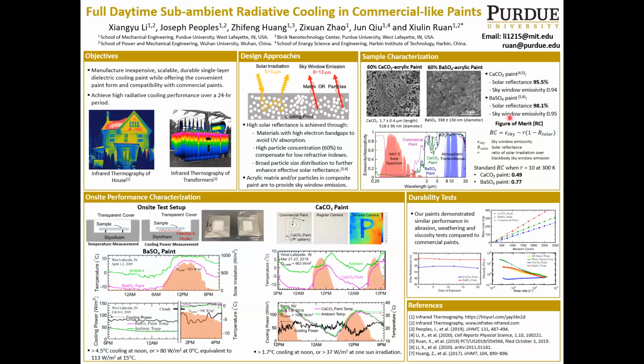We propose a standard figure of merit for radiative cooling as RC to include both sky window emission and solar reflectance. R is the ratio of solar irradiation over black body sky window emission, depending on different locations and weather conditions. With a positive RC, the coating is capable to reach full daytime cooling. A standard RC is defined when R equals 10 with coating temperature of 300 Kelvin. Our calcite and barium sulfate paints reach 0.49 and 0.77 standard RC, which are the highest among paints.